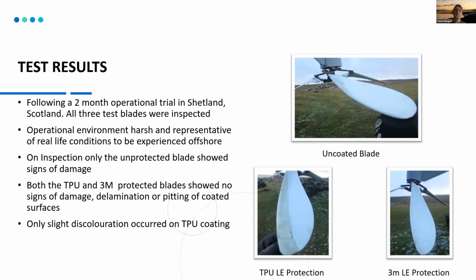So we did some trials in the lab. We also made some blades and put them on a small wind turbine in Shetland. We tested a blade with the market leader, which is 3M leading edge protection. We did an uncoated blade, and we did thermoplastic polyurethane, which was the solution we were looking at the most. The trials showed that there was some damage on the unprotected blade, but it was pretty early on in the trials. Really you'd expect to see damage probably after a year or after a couple of years. And so the trial is still ongoing.